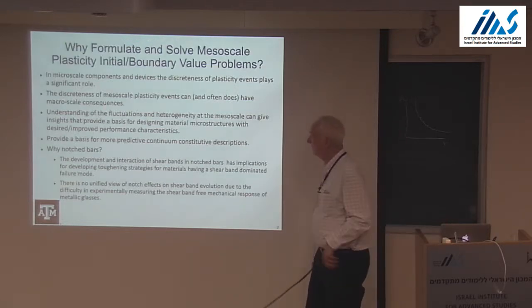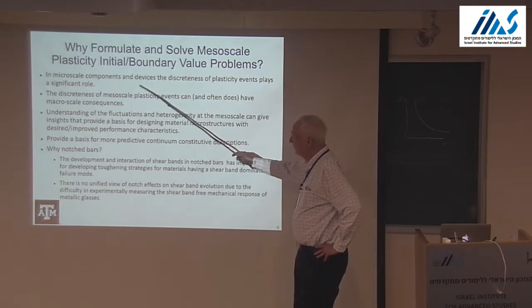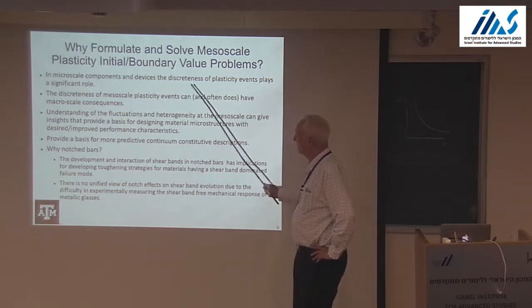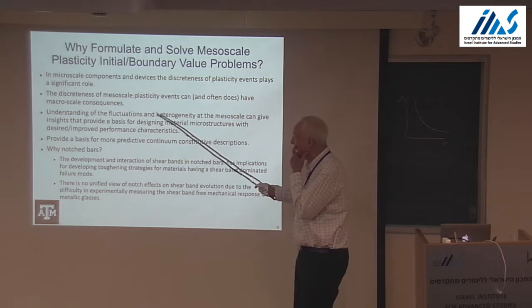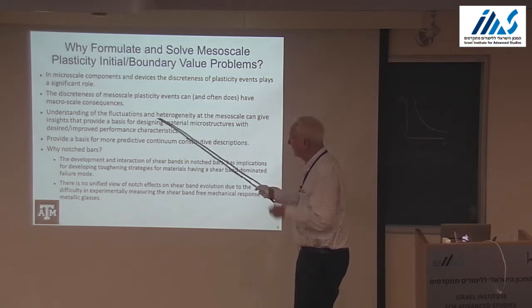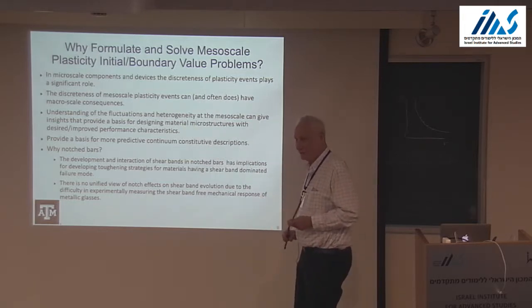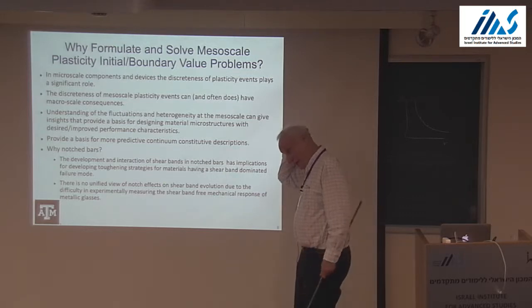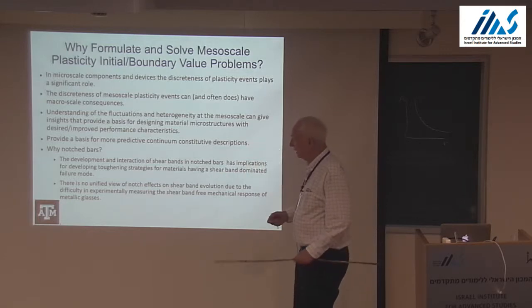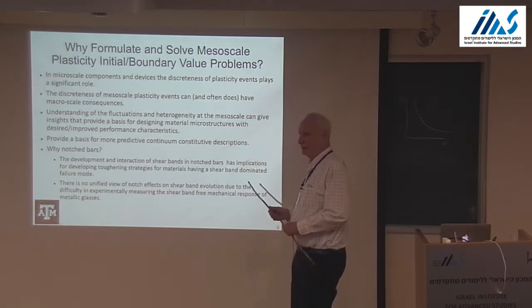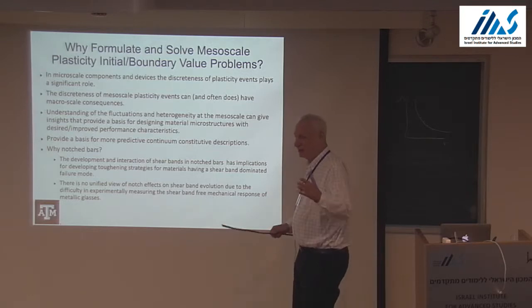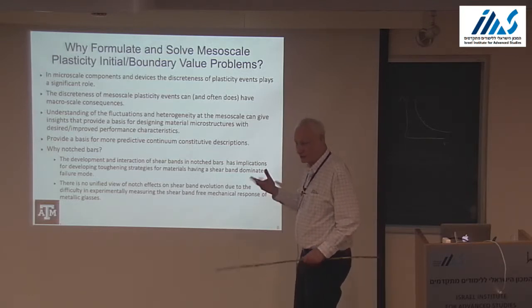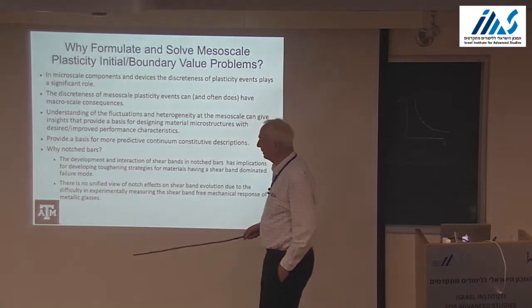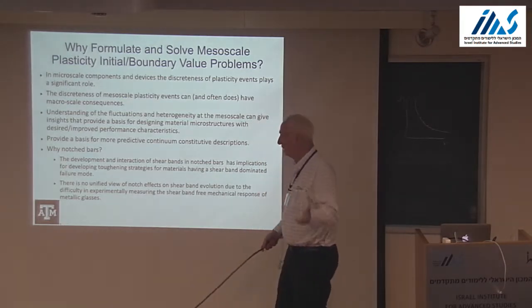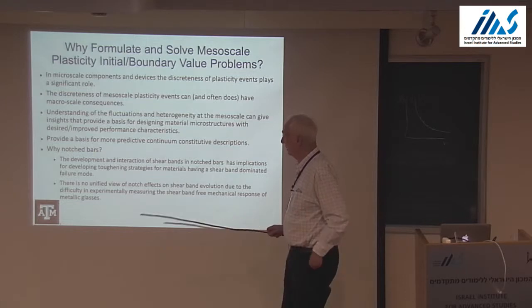And why? From an engineering perspective, in microscale components and devices, the discreteness can play a significant role. It can even, and often does, have macroscale, very large scale consequences. Examples include dislocations around crack tips. Dislocations form organized structures that lead to very high stresses, have a big influence on fatigue, and can have an influence on things like hydrogen embrittlement.